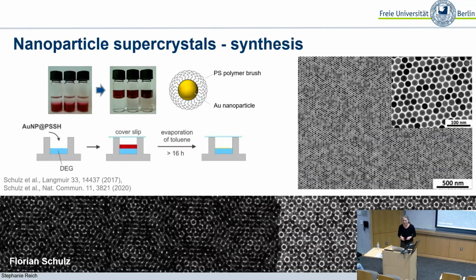Now let's see whether we can actually realize this. For that, we started to team up with collaborators from the university in Hamburg. I really want to mention Florian Schulz in particular, who developed this entire concept of nanoparticle synthesis and supercrystal growth. What he was working on when we met was to grow gold nanoparticles with essentially the standard techniques that people use, but he tried to make them bigger and more uniform. In order to achieve that, first he was very careful in controlling the conditions that he used for growth. And he also used a new type of ligand to stabilize these gold nanoparticles so that they don't agglomerate in solution. The ligand is essentially a polystyrene brush that he attached to the surface of the gold nanoparticles, and these polystyrenes are great for stabilizing them.